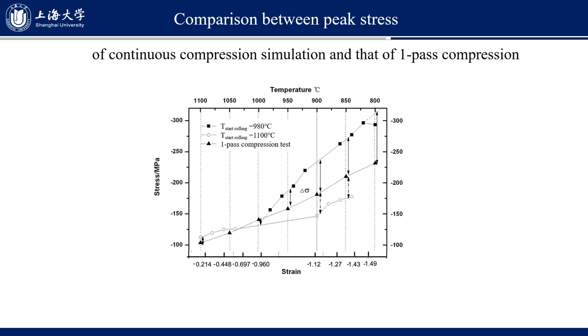975 degrees C. This slide shows the comparison between peak stress of continuous compression simulation test and that of one-pass compression test. Compared with the one-pass compression test result, the multi-pass compression test conducted with a start rolling temperature of 1100 degrees C shows a quite lower peak stress at a later stage. However, for 980 degrees C start rolling temperature, the peak stress is very high compared with that of the one-pass compression test.